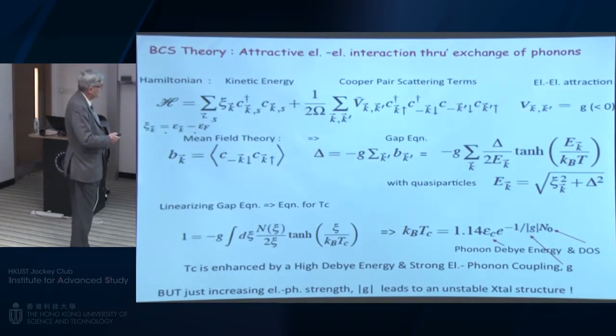So this is a quick outline of this theory. I don't want to go through it in detail here. It starts with a model of kinetic energy for one electron, and then introduces scattering between electron pairs. And the pairs are electrons with a total momentum of 0, on opposite sides of the Fermi surface. And when you have an electron attraction, if you do a mean field with the pairing amplitude as the mean field, you get a gap equation which can be straightforwardly solved, and you get a formula for the transition temperature, which has a prefactor related to the cutoff in energy associated with this attraction, because this is, as I said, mediated by the phonons.